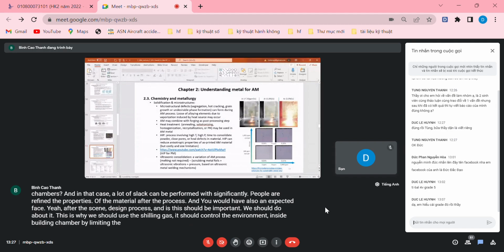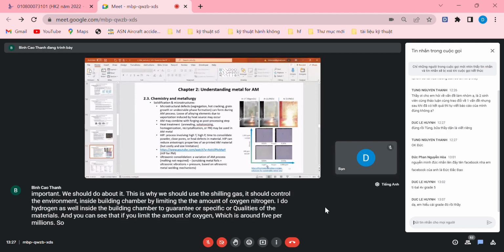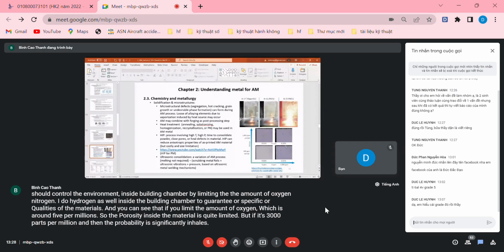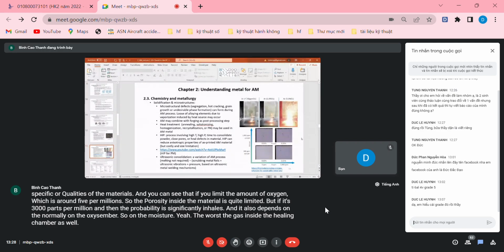This is why we should use shielding gas. We should control the environment inside the building chamber by limiting the amount of oxygen, nitrogen, and hydrogen inside the building chamber to guarantee specific qualities of the materials. You can see that if you limit the amount of oxygen to around 5 parts per million, the porosity inside the material is quite limited. But if it's 3,000 parts per million, the porosity is significantly enhanced. It depends not only on the oxygen but also on the moisture, the water vapor inside the building chamber as well. Again, the environment inside the building chamber must be controlled in order to guarantee specific qualities of the materials.